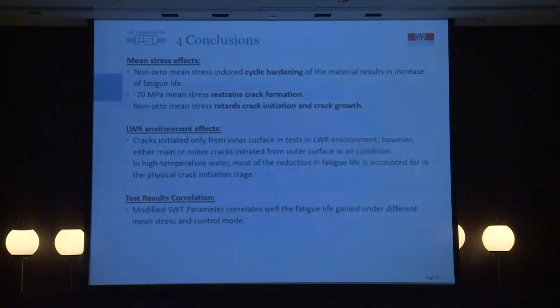So finally, we go to our short conclusions regarding the mean stress effects and the light water reactor environmental effects and the test results correlation. We found a non-zero mean stress induced cyclic hardening of the material and resulted in an increase of fatigue life. The minus 20 MPa mean stress restrains crack formation, and the non-zero mean stress retards crack initiation and crack growth. In the light water reactor environment, the cracks initiate only from the inner surface in tests in the light water environment. However, there are minor cracks initiating from the outer surface in the air condition.